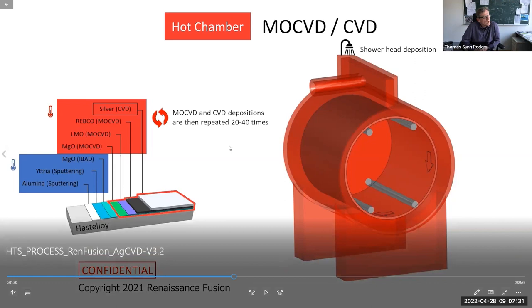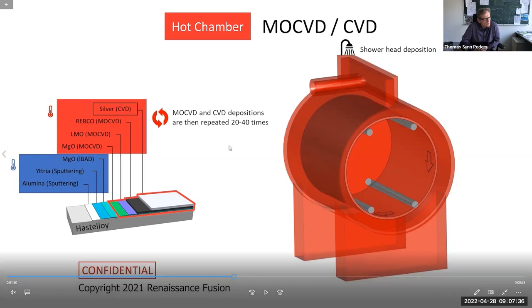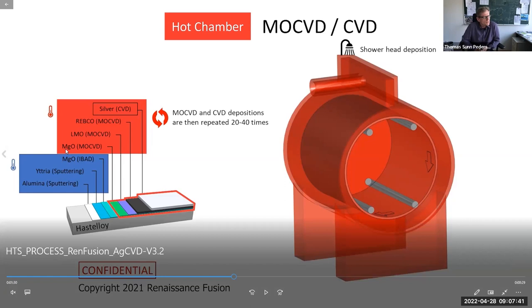Okay. And you're using magnesium oxide as your superconductor. No, magnesium oxide is a buffer. The REBCO is the superconductor. It's the REBCO you're using as the superconductor. Yeah. The magnesium oxide is the textured interface layer that, with the LMO in between, causes the REBCO to grow in the right crystalline structure so that you have the highest IC.